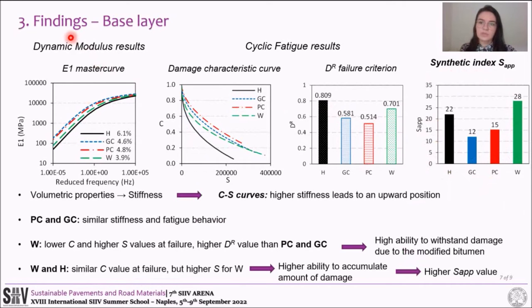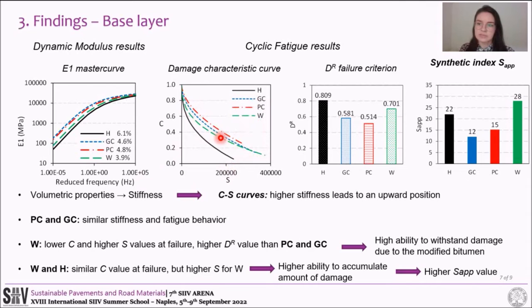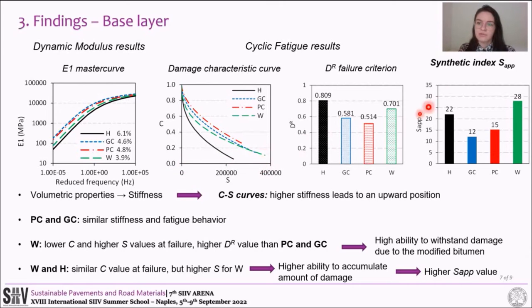Regarding the base layer, from the dynamic modulus master curve it can be observed that PC and GC have comparable stiffness, followed by W and H, mainly due to volumetric properties. A higher stiffness leads to an upward position of the C-S curve. GC and PC have similar fatigue behavior, worse than H, because of higher C values at failure and lower DR values, indicating low ability to withstand damage, likely due to the unmodified bitumen. W and H reach a similar pseudo stiffness value at failure, whereas W is capable of accumulating a higher amount of damage S. Finally, the Sapp ranking confirmed that obtained from the binder cores: better fatigue performance is expected from the warm mix, followed by the reference mix, and finally the two plastomeric compound mixes.